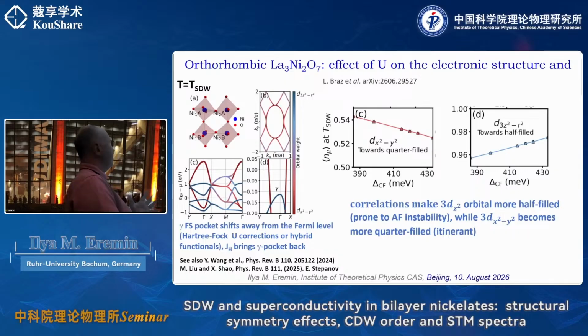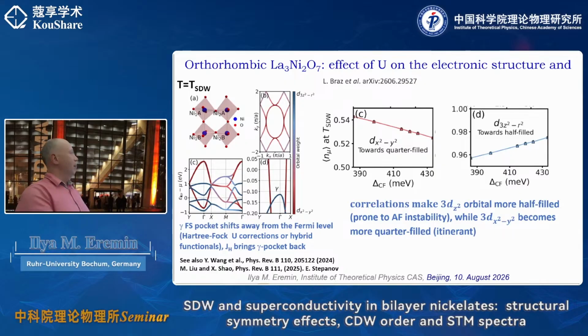But what you effectively see is that eventually, and it's also a function of U, the reason why the system wants to gap out the gamma pocket is because the dz square orbital wants to become exactly half filled. Because if you start from the DFT, the filling is about 0.96, but that's when you plot it on the itinerant level. But once you include the Hubbard U correction, even on the Hartree-Fock level, you see that the filling on the dz square wants to become half filled. And that's nice because effectively it also tells you that the main correlations are playing on the dz square orbital.